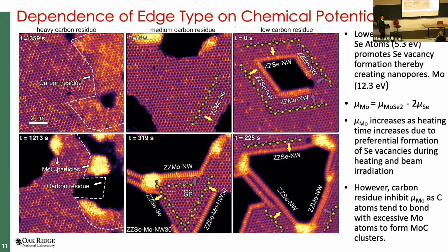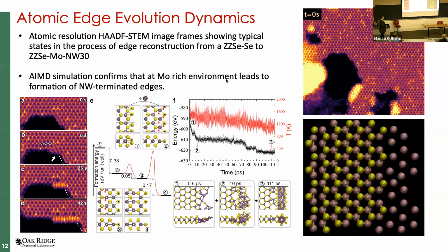Because it's more prone to knock-on damage than the heavier moly atom. So what we say is here, we can calculate what the energy is to knock out a selenium atom versus moly, and it's a lot lower. Like it's 5.3 eV versus like 12.3 eV. So we can kind of make this correlation with a chemical potential. If I start knocking out the chalcogen atoms, I start to enrich the area with moly, and the chemical potential starts to increase. So this is basically our driving force, and I'll talk about phase diagrams in a second. So as we're heating it, either with heat or the beam, you're kicking out the easier to remove chalcogen atoms. You're creating these vacancies, and your chemical potential increases. So some of that happens where you start to form these carbides, but this again, this is where I'm interested, and I'll take a little deeper dive in that regard.